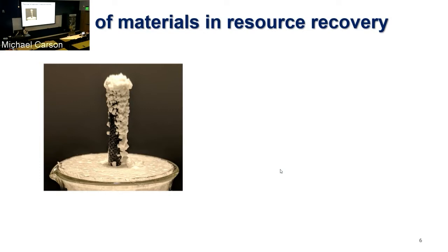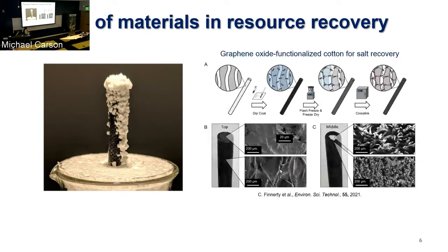And what you see is if you continuously evaporate the water, at the end of the process, you have salts which will precipitate on the surface. So this is one potential option to do lithium extraction from seawater, for example, a very passive process. And because lithium and sodium have very different solubilities, you could exploit that difference in solubility in order to get lithium precipitation. Again, this relies on designing your material with very specific characteristics.